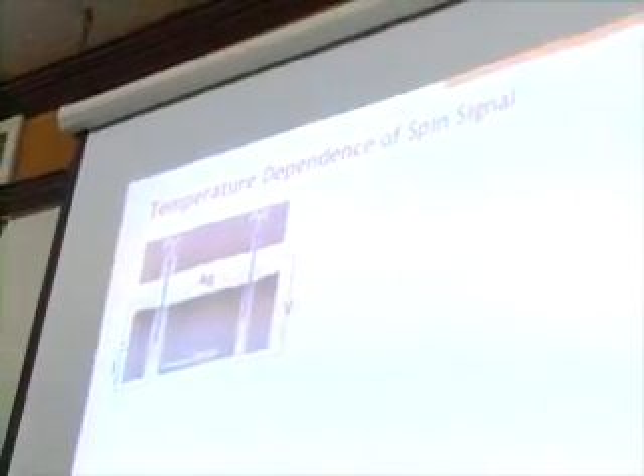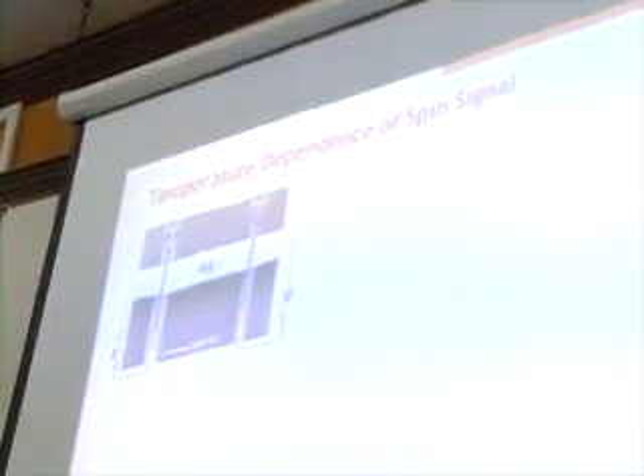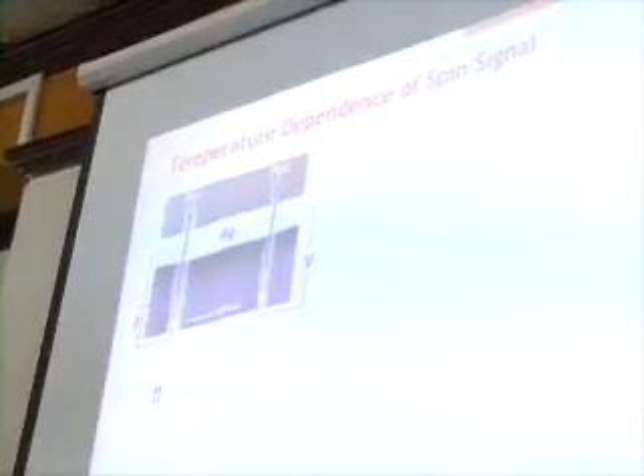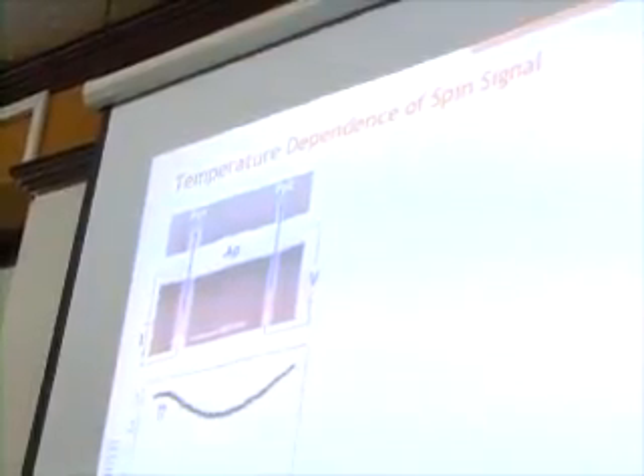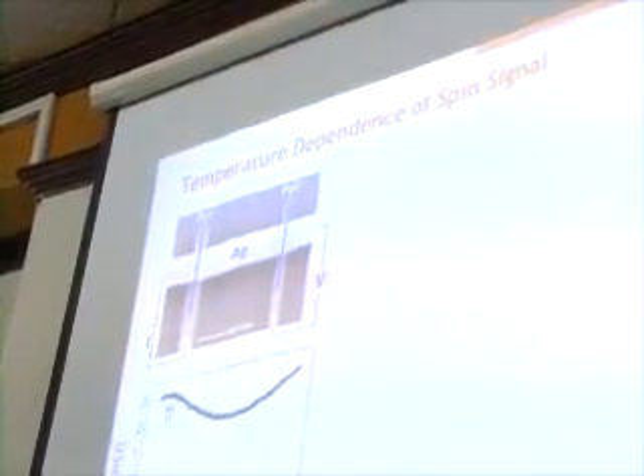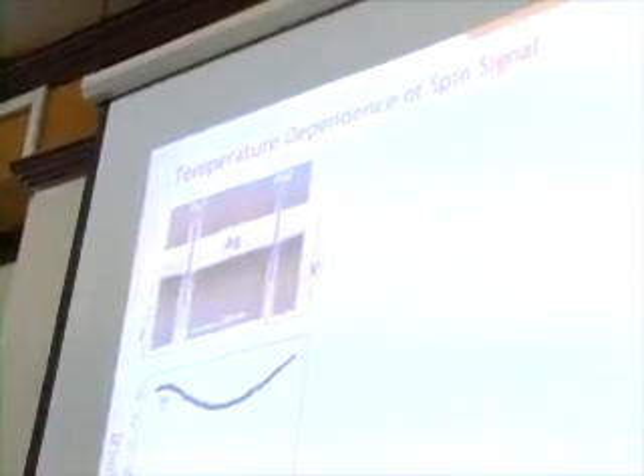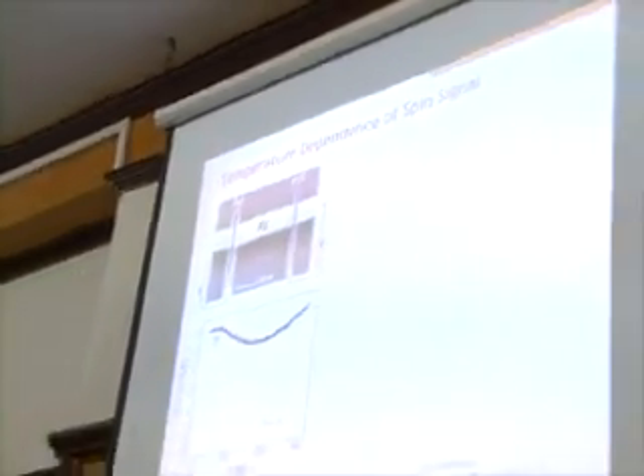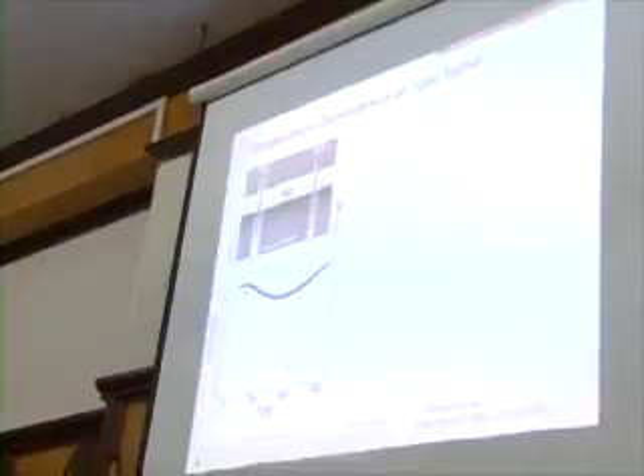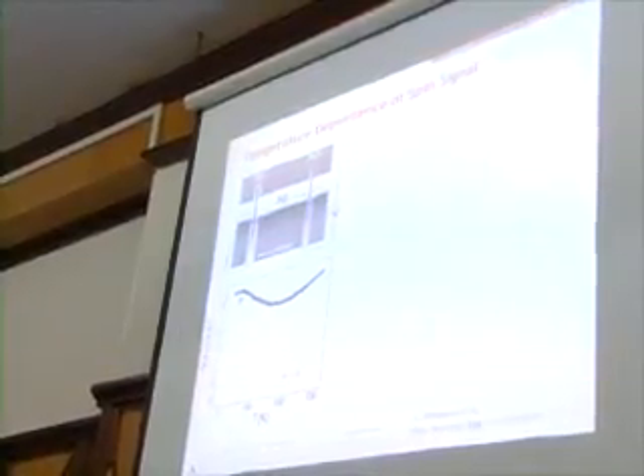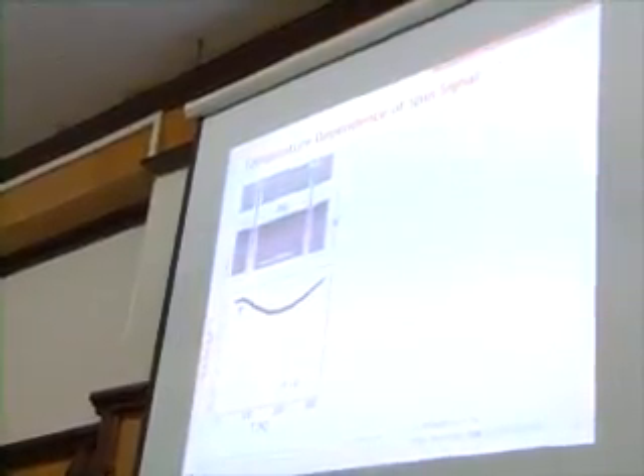So what we do is we take these devices, we apply the fields so that the magnetizations are parallel to each other. We move the field, and then we measure the spin signal as a function of temperature. And this is shown here. Here's the voltage as a function of temperature. And what you see is the spin signal is kind of non-monotonic. It goes down and then goes up. And so that looks very interesting, maybe something interesting going on.